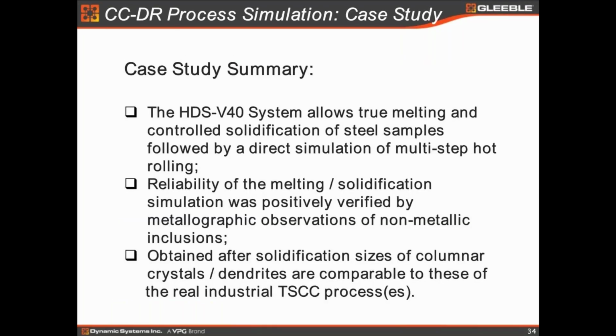Okay, so these are the examples of the case study, and I want to make a conclusion for this case study. I mentioned it already, but I want to summarize it. Firstly, the HDS V40 really can simulate the true melting and solidification situation that you see in your real process, followed by a multiple-step hot rolling process, as you see in your project flow. Also, the reliability of this simulation process is very positively verified by the metallographic observation, as we can see using the non-metallic inclusions. And as I just mentioned, the columnar grain size that we achieved using this methodology is comparable to what we see in the industrial thin slab continuous casting process.